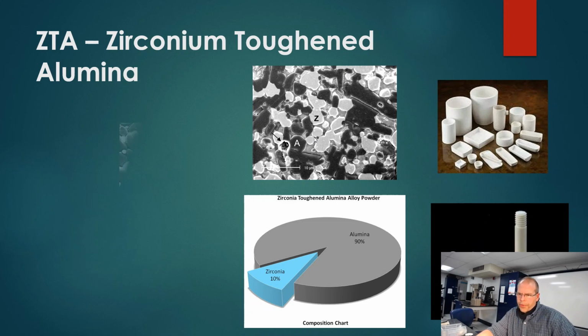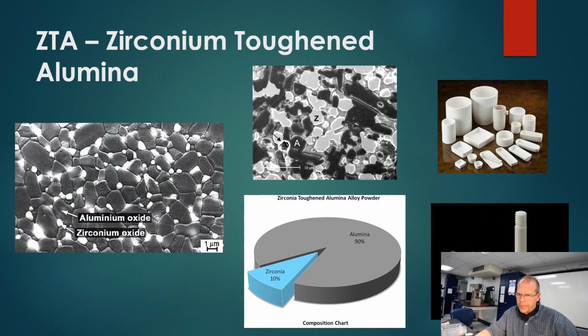One very cool thing that Professor Sheldon is going to talk about, and again, you can see a better SEM picture. I wish that my samples actually looked like this. Here you can see a perfectly sintered sample. When I say sintered, I'm talking about heating to very, very high temperatures. You'll notice that here you don't see any porosity. Unfortunately, with the oven temperatures that I'm going to be dealing with, we won't get samples as good.